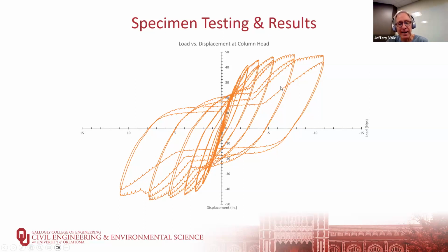We do still get buckling eventually of the steel tube. And again, when that reverses and the buckle comes out, you start picking up capacity. And we only get a decrease from about 49 to about 42 kips with the steel tube buckling. Now, eventually, if we were to cycle this thing back and forth up to that almost 11-inch displacement, that steel tube is going to fracture. It's like when you take a paper clip and bend it back and forth and back and forth and back and forth, right? That's what's called low cycle fatigue, high stress, low number of cycles. Eventually, you would fracture that steel tube. But for this application, it's going to buckle locally and then straighten out.